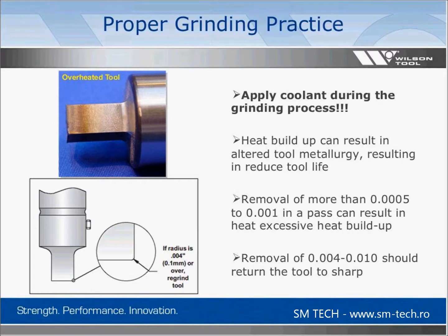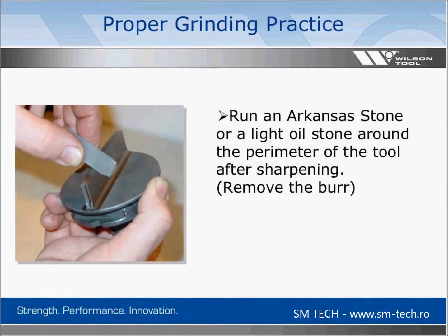We recommend making very light passes with your grinder, only removing 5/10 to a thou in a pass, otherwise that excessive heat buildup can occur. When that heat buildup occurs, the tool can actually become brittle, or on the opposite end, it can actually become soft, and the tool will wear down much faster. You should never have to remove more than 4 thou to 10 thou of material in any given sharpening. After you've sharpened the tool, we recommend running an Arkansas stone or a light oil stone around the perimeter of the tool. This is to remove the burr.